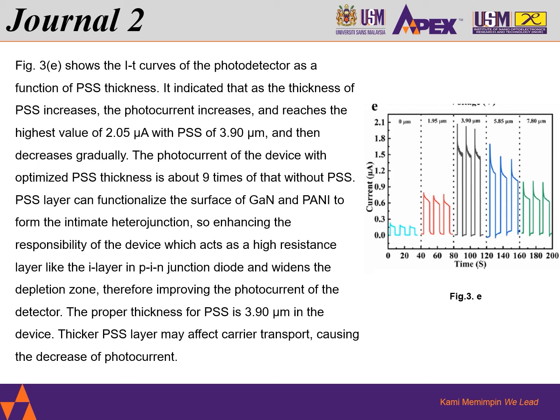Figure 3e shows I-T curves of the photodetector as a function of PSS thickness. It indicated that as the thickness of the PSS increases, the photocurrent increases and reaches the highest value of 2.05 microampere with PSS of 3.90 micrometer, and then decreases gradually. The photocurrent of the device with optimized PSS thickness is about 9 times that without PSS.